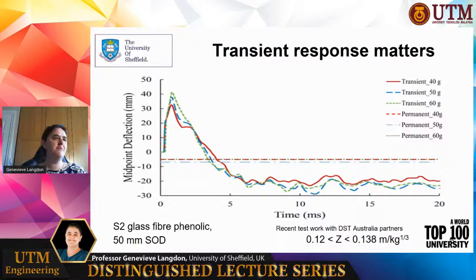We were able to do some work with partners from Australia who supplied the panels. When I was at Cape Town, we did these experiments quite recently, where we looked at S2 glass fiber and subjected it to quite near field loading, quite extreme loads: 40, 50, and 60 grams, all shown on this picture. What you can see here is the midpoint displacement against time. It starts off at zero, goes up to a peak, and the peak increases with increasing charge, which you may expect. And then you get this rapid rebound afterwards.